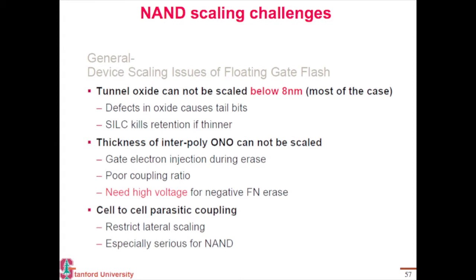Tunnel oxide thickness has become very difficult to scale, especially below 8 nanometers. The reason is because, as I described earlier, if you have a thin dielectric, you get a lot of defects in it, and you get stress-induced leakage, which tends to kill your retention of the cell.